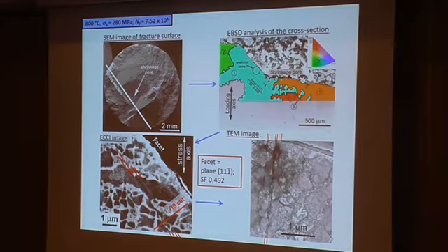Temperature is 800 centigrades. I chose another specimen and we did the same procedure. Again, EBSD analysis in this area. I found the localization of plastic deformation. Here is visible slip shearing of precipitates. And this is the area of the FIB cut where I extracted the transmission electron microscopy foil.